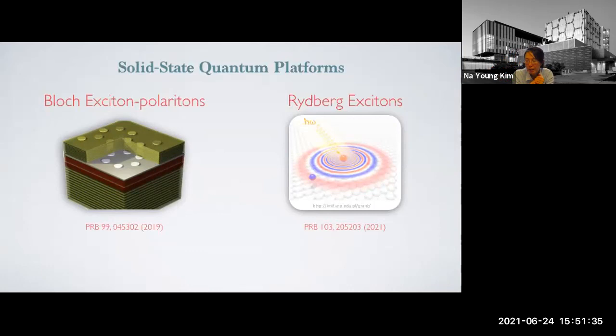And the Rydberg exciton in this case is, in fact, a p orbital, because of this band structure, the s orbitals or the d orbitals are prohibited by dipole interactions. In the photoluminescence case, what we observe is that the p orbital Rydberg states are immediately transferred to the 1s, the photoluminescence states, through the phonon, because of the phonon background, so there are a lot of phonon emissions and absorption, so we have not seen the photoluminescence in the Rydberg exciton states directly because of that.